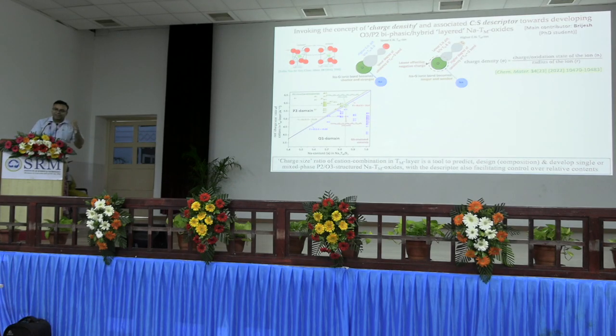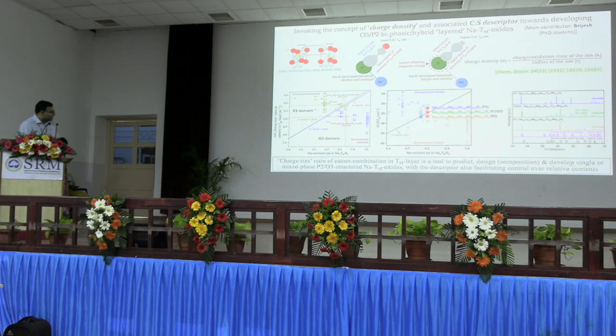So now, again, the same concept, I told that I will use the same concept to show a few things. There is a lot of effort on designing and developing these hybrid layer transition metal oxides, P2/O3, P2/P3, etc. Now all those can be designed based on this chart again, the charge to size ratio versus the sodium content. If we use this, we can design compositions which can form P2, which can form O3, and which can form P2/O3, and if we just follow that, we got exactly that when we synthesized this material. So, 3 minutes, yeah, sure, thank you. This concept of covalency of the transition metal oxygen slab and the charge to size ratio can also be used for scientifically developing the hybrid layer transition metal oxide structures. So depending on what we want, a biphasic material and the sodium content, we have to follow this line and we can get the material.